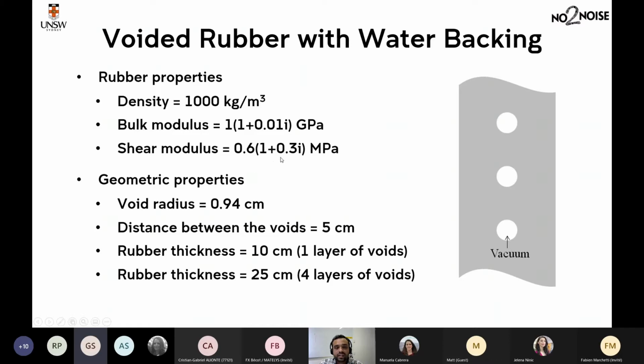And you will also see that the shear damping in the material is very high compared to the damping of bulk waves in the media. And this is very common for soft media. These are some geometric properties. The void radius is 0.94 centimeters. I chose this for one of my papers, but it's just a random number. Distance between the voids is 5 centimeters. So the center to center distance here is 5 centimeters. Rubber thickness, for the case when you have one layer of voids in the direction of sound propagation, is 10 centimeters. And when you have four layers, it is 25 centimeters. So if you have extra layers here, the center to center spacing in the direction of sound propagation is also 5 centimeters.